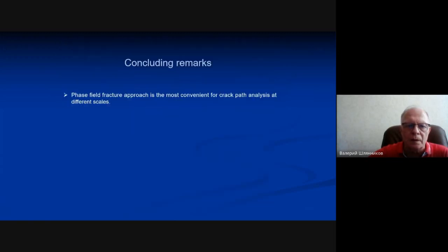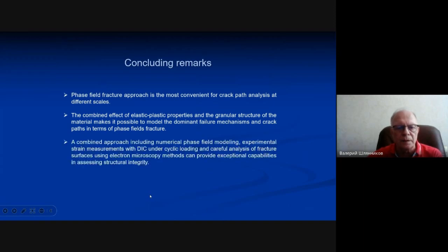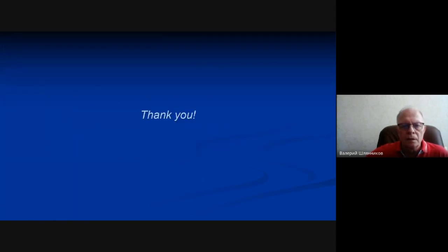And concluding remarks. The phase field fracture approach is the most convenient for crack path analysis at different scales. The combined effect of elastic-plastic properties and the granular structure of the material makes it possible to model the dominant failure mechanism and crack path in terms of phase field fracture. And last, a combined approach including numerical phase field modeling, experimental strain measurements with DIC, cyclic loading, and careful analysis of fracture surfaces using electron microscopy methods can provide exceptional capabilities in assessing structural integrity. Thank you very much for your attention.